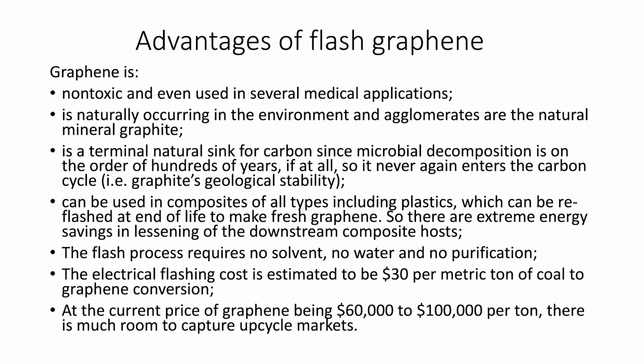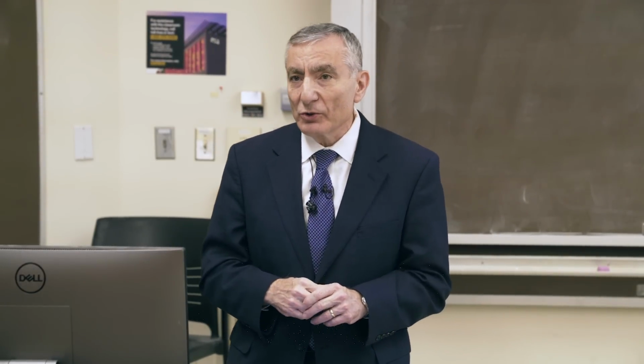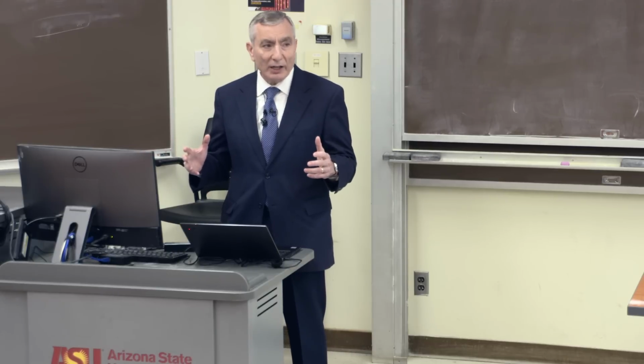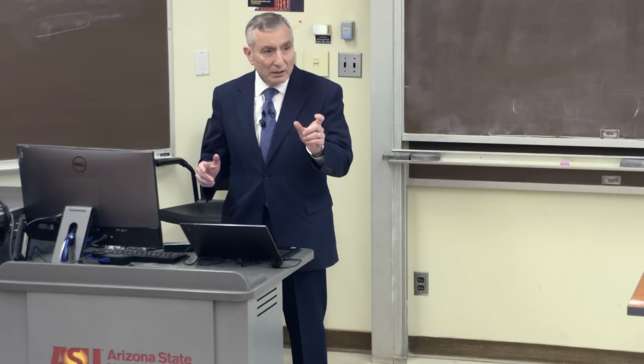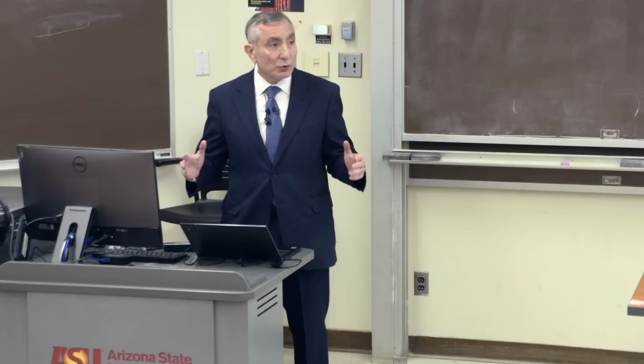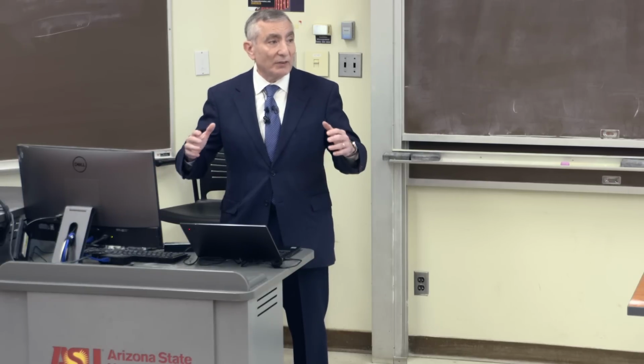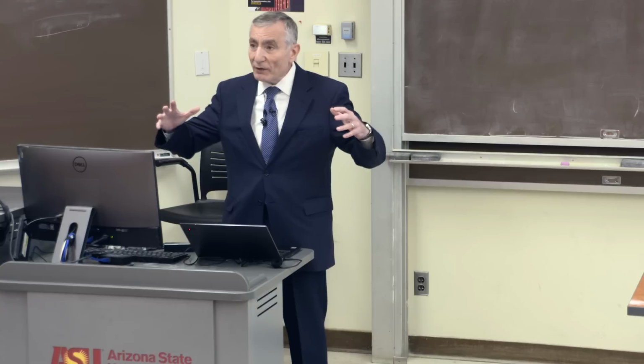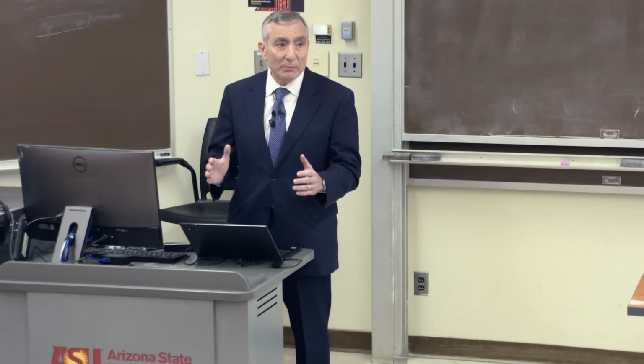The electrical flashing cost, you say it must take a lot of energy. No, it doesn't. It takes about $30 per metric ton of coal, $30 in electricity. You say, well, don't you use a high voltage and a high current? Yes, but for very short amounts of time. We're not heating a big furnace, which is normally done with furnaces. You have to heat that whole system. Here we're driving all the energy right on into the material.